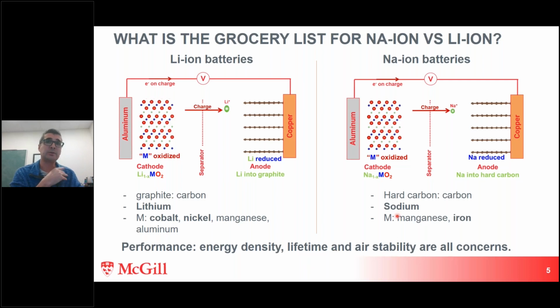And another issue that comes up with the sodium ion cathodes that doesn't with the lithium is air stability. So if we make these materials and then store them in a package while we ship it halfway around the world before we put it in a battery, these can decompose. And they decompose into things that are no longer good battery materials. So we're working on all three of these in my group. So this is what I'm going to talk about for the rest of my talk.